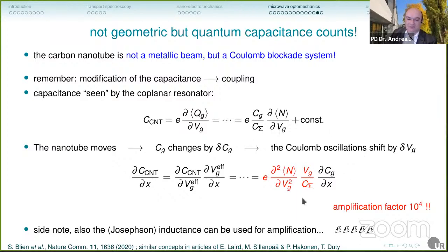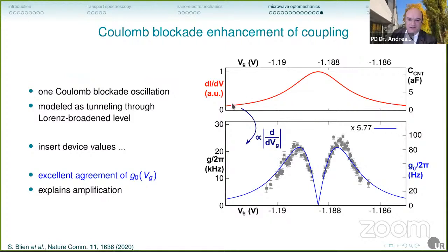We can plug numbers into this model. So here we have one Coulomb oscillation modeled as tunneling through a Lorentz-broadened level. We insert our device values, and we get really a nice agreement of the evolution of the optomechanical coupling parameter with this theory curve. And even the absolute values fit rather well, given the many assumptions that went into the model.